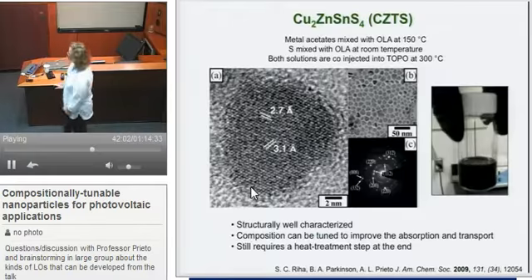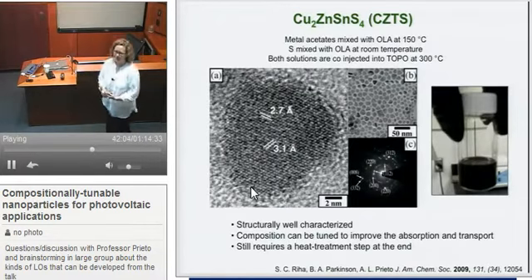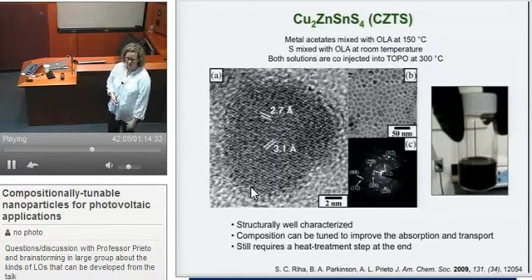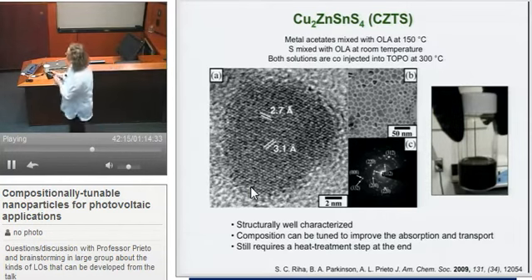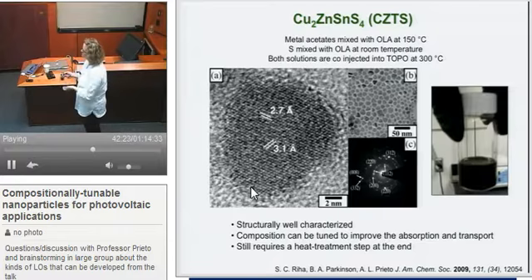Now in our case, I'll tell you how we thought about the synthesis. I think we were very lucky that it worked the way that it actually did, and then I'll add a commentary to something that Ray said about things changing and you can't necessarily control it. So the way we thought about it actually is as an electrochemist. So a lot of what we do in my group is electrochemistry, so I tend to think about oxidation state. So if you look at the compound here, copper 1+, zinc 2+, tin 4+, and sulfur 2-.